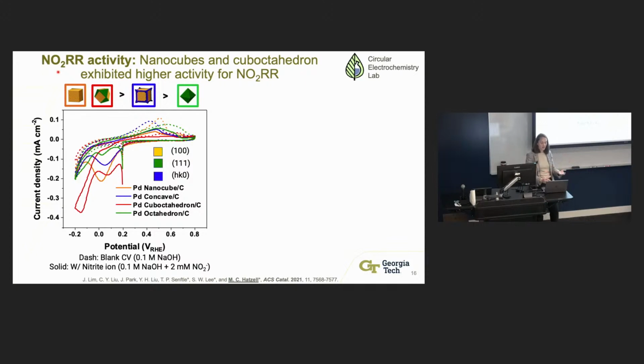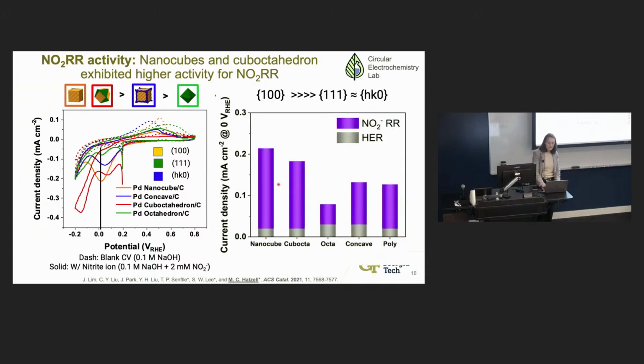So unsurprisingly, it's pretty excellent, and it doesn't really matter which facet you have. You're getting pretty similar performance. I mean, the nanocubes seem to have slightly enhanced performance, and so it seems like the 100 facet is slightly better for the nitrite reduction, but in general, we're not really worried about palladium in this reaction. But there is some surface structure effects.